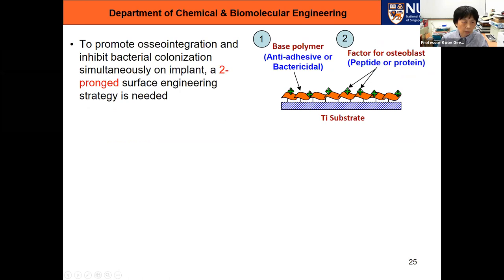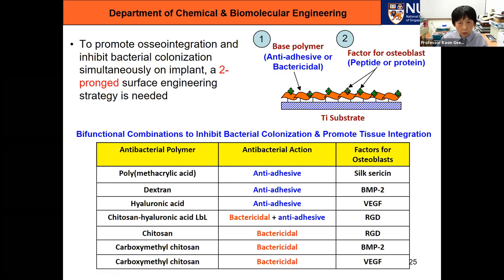So in order to deal with both problems simultaneously, we again need a two-pronged approach. The first thing to do is to have a base polymer that takes care of the bacteria. In other words, it can be anti-adhesive, it can be bactericidal, but we need something else to take care of the osteoblast. So we need a peptide or a protein. This table pretty much summarizes what we have tried. On the left-hand side are the various antibacterial polymers. These polymers can be anti-adhesive, bactericidal, or a mixture of both. And on the right-hand side are the factors that we have tried for osteoblasts. So I'm just going to show one example.